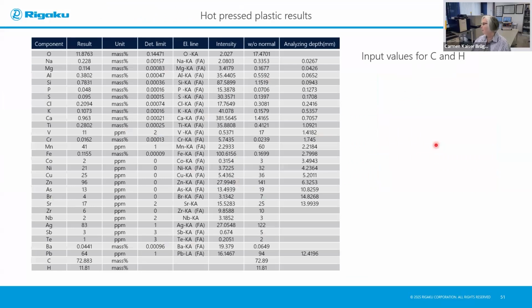So, of course, the analysis of that material that you saw now is shown here. But this analysis is slightly different in that we measured carbon and hydrogen by another technique, and we put these values as a fixed input into the analysis of the semiquant. So as you can see, this would be the analytical results for that kind of hot pressed plastic, and where we, of course, always need to look at not only the analytical result, but detection limits that we get.